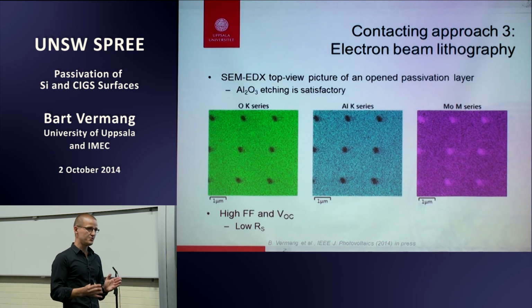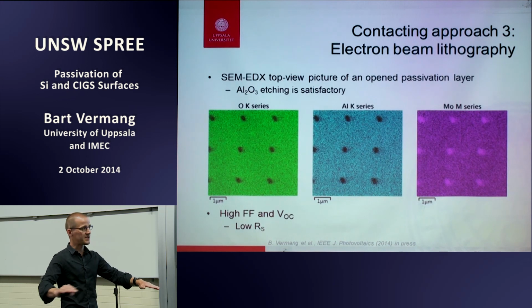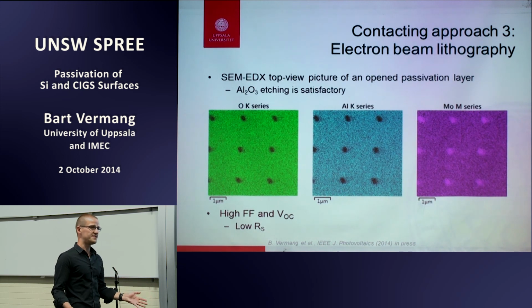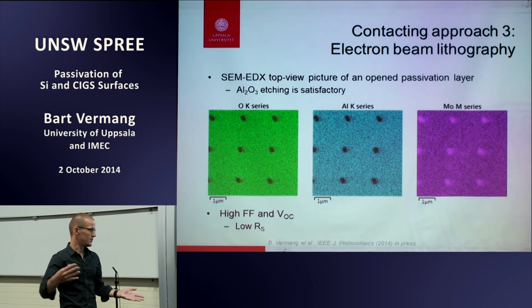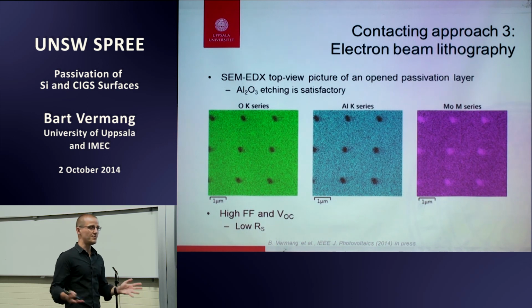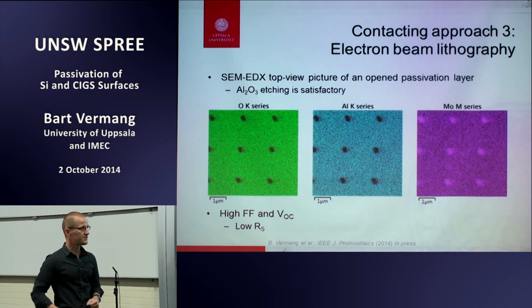So what we did there was, it was 2 to 4 nanometers of aluminum oxide. We compared cells with the full aluminum oxide passivation layers and cells with only the passivation layer and the openings. And you could clearly see the ones with the full layer were just extremely crappy cells, had a fill factor of 16%. So there, the blocking effect of the aluminum oxide layer was very, very clear. While for the cells with the openings, we got normal fill factors, higher VOCs, similar JSCs because it was a very thin layer, so no reflection. So that was the first moment we could somehow indicate, look at this passivation layer, we think it works. And then we got more and more results.